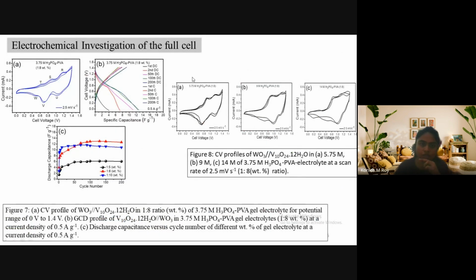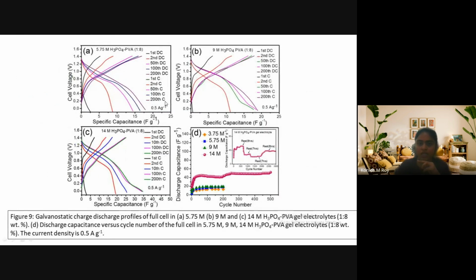So moving towards the full cell setup, we took the cathode as V10O24 and the anode as WO3 in different gel electrolytes. At first, we started with 3.75 molar H3PO4 gel electrolyte, and here we could see that 1:8 was showing better results. So we moved forward with 1:8 weight percentage for higher concentrations of the gel electrolyte, as we wanted to prepare a gel in an acid kind of solution. As we increased the concentration, we could see that the performance also increased.